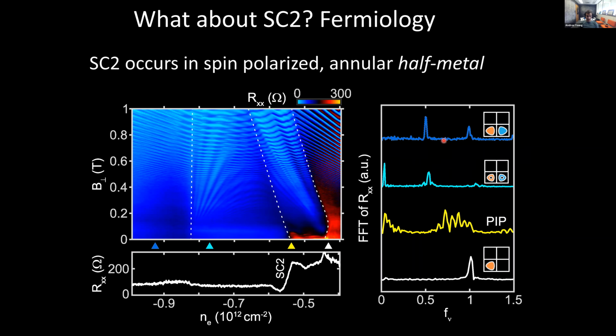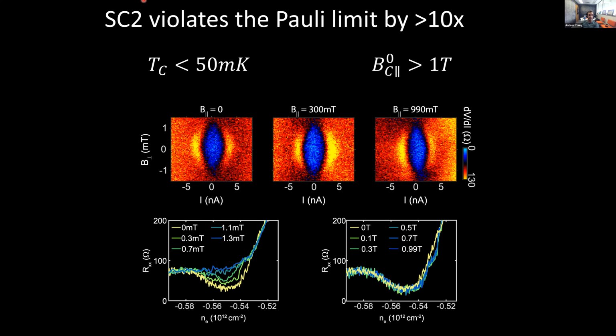Quantum oscillations in this regime show a half metal, so a strong peak at 1/2, which means 2 simple Fermi surfaces. And then we enter a region where we have annular Fermi surfaces, but again, 2 of them. So you have a peak at low f_nu and then a peak at slightly higher than 1/2 f_nu, exactly as in the first case. And then the superconductivity seems to happen just on the border before you enter some kind of partially isospin polarized phase. Okay, so in many ways it's analogous, except that now we're actually in a fully spin polarized metal. So we're in a half metal in the sense that we only have one projection of spin, and yet we have superconductivity. So certainly that is not a normal situation for a superconductor. And you can see that indeed this SC2, the second superconductor, violates the Pauli limit by a very large factor.